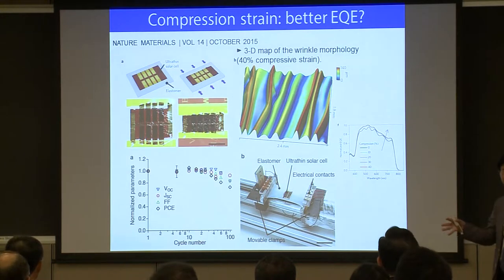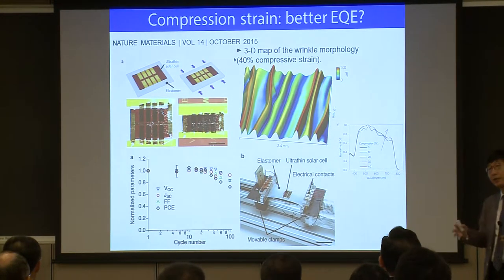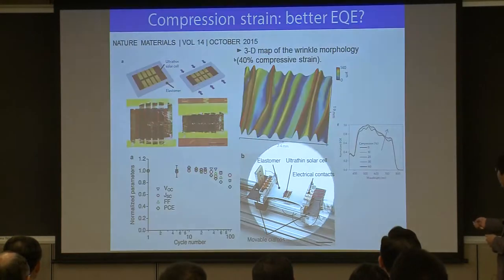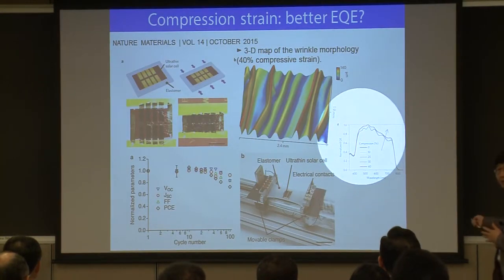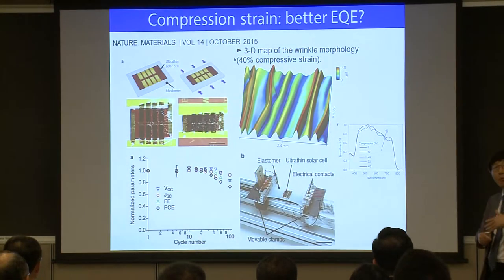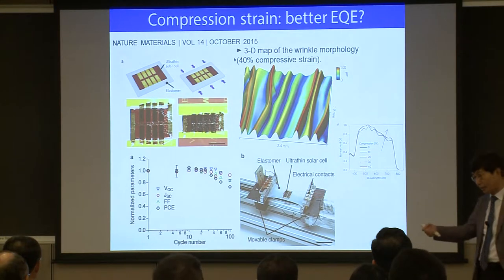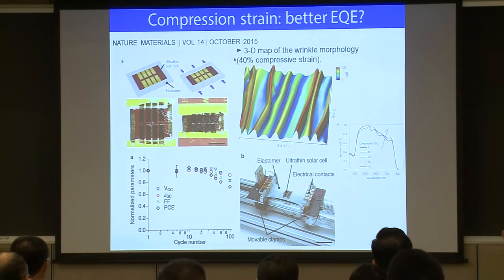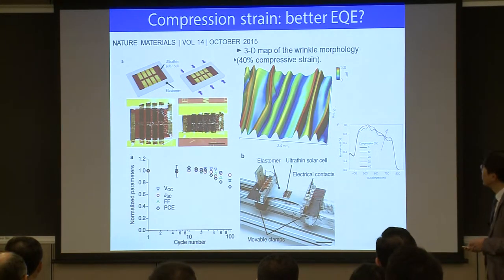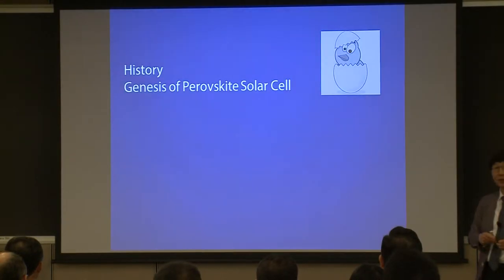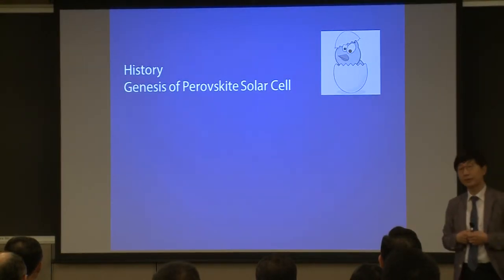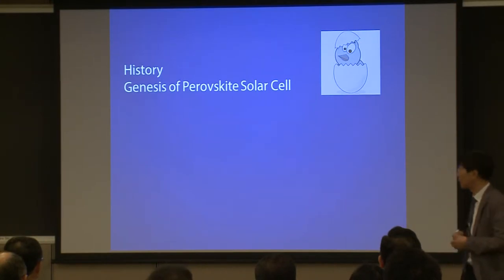And also, if you compress some perovskite solar cell, then the external quantum efficiency increases, meaning that you have more photocurrent density. The other way around, if you stretch out the perovskite solar cell, then the photocurrent density decreases, which cannot be explained exactly using conventional semiconductor physics. So anyway, this material is very interesting in terms of its physical property, optoelectronic property.